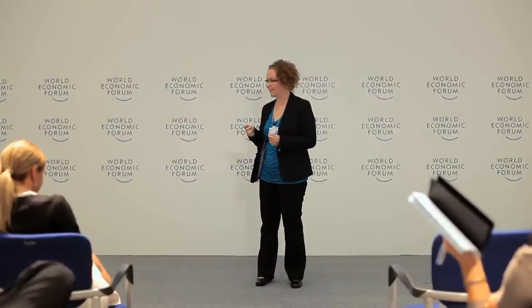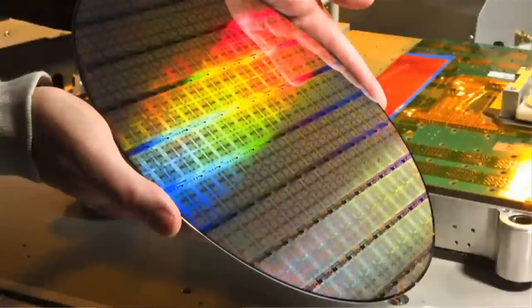I have background in microelectronics. Previously, I noticed that in these devices, different light sources caused troubles for device operation. In most cases, the root cause was found to be ionized copper. Having this in mind, I raised the question if the solar degradation we observe in panels today is due to ionized copper. What I'm excited about is the solution I'm proposing. We know that copper is positively charged and moves very easily in silicon, even at room temperature. Positive and negative charge attract each other. So what if we put some negative charge on the solar cell surfaces? We can get rid of this harmful copper. Actually, our preliminary results are quite promising.